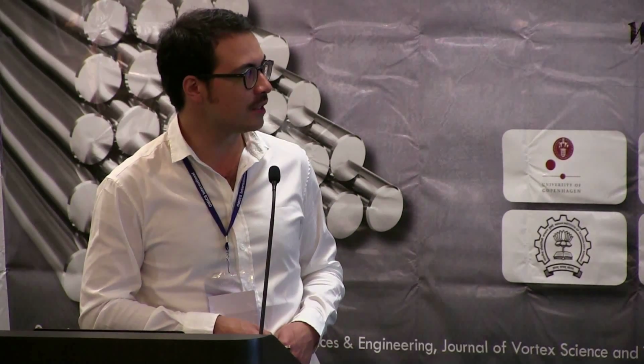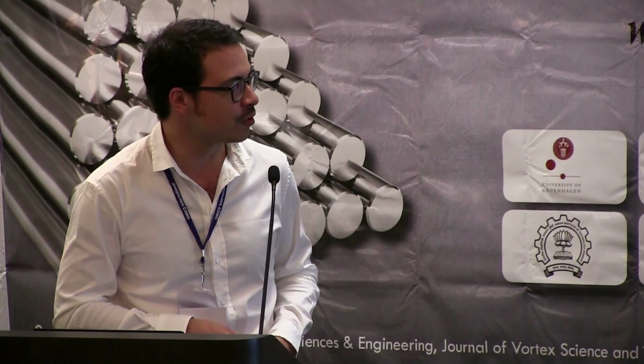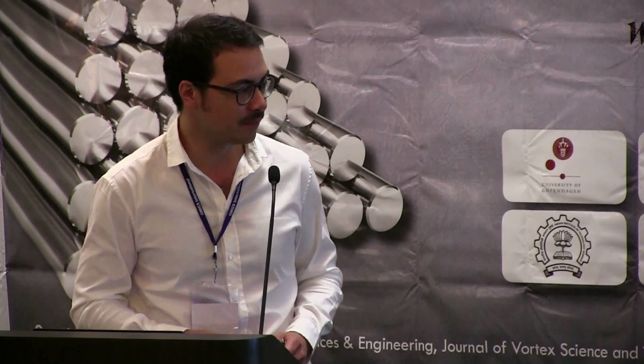So you see this is the gray line. This is an optimum wire of SAES Getters as it has to be. It makes a displacement of about 4 millimeters, and our wire had a small drift directly in the first cycle of 1 millimeter, but then it had the same behavior.